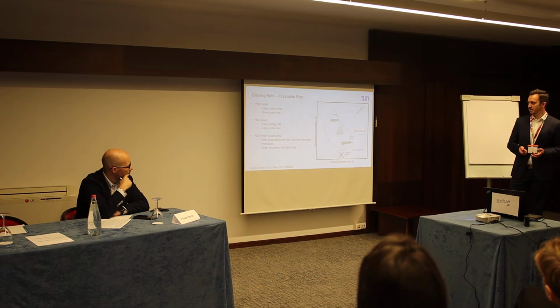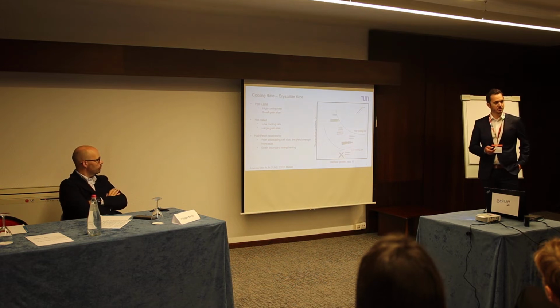And to put that into respect to the yield strength, we can use the Hall-Petch relationship, meaning that with decreasing cell size, the yield strength increases. This is also called grain boundary strengthening, which has a nice side effect that we have nearly the same elongation at fracture, meaning that it doesn't become very brittle.